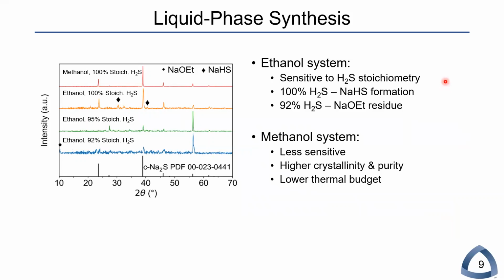However, we found that the synthesis in the ethanol solvent was fairly sensitive to H2S stoichiometry, with 100% of H2S resulting in formation of sodium hydrosulfide byproducts, whereas 92% addition of H2S resulted in residual sodium ethoxide crystallizing in the sodium sulfide product, with 95% of the stoichiometric being found to be the optimal stoichiometry, resulting in nominally phase-pure sodium sulfide.